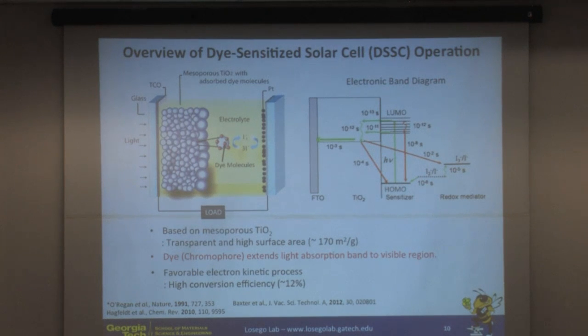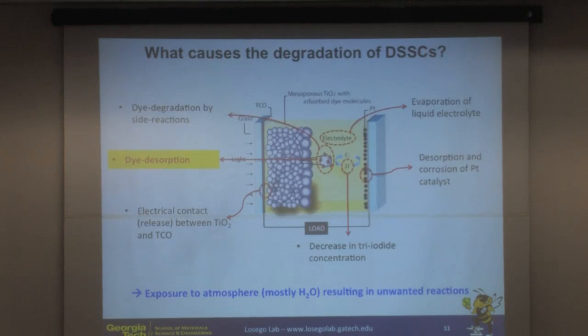So first, a bit of an overview for a dye-sensitized solar cell, so everyone's on the same page here. Dye-sensitized solar cells are nanostructured devices where you attach dye molecules that absorb light. So light comes in, and in the molecular electronic orbitals, an electron gets excited from the HOMO to the LUMO, and it gets injected into the inorganic nanostructure. This process needs to occur to then collect the charge on the electrode and run the device, whatever the load happens to be.